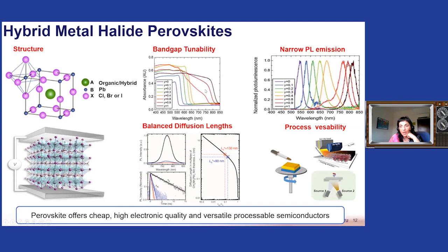But also, if you keep the iodine constant in this configuration in your X, and you just change the organic compound, it can also bring a change of colors in the perovskite. So when you change either the iodine content or the cation content in this part, you can change the composition. There are some changes that are more efficient than others. For example, chloride and iodide substitution is usually the fastest way